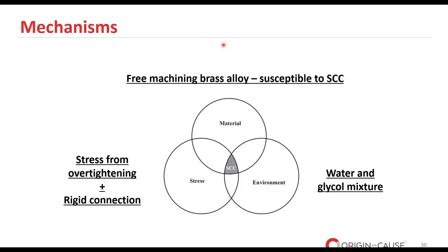So here's our SCC Venn diagram once more. On the one side, we have our brass alloy that's susceptible to stress corrosion cracking. The component's persistent exposure to the water and glycol mixture introduces another layer of concern. And also the combination of over-tightening induced stress and the rigid connection fostered some stress accumulation here. So we have our three requirements for stress corrosion cracking: stress, a susceptible material, and the environment, and these all collaborate to increase the risk of stress corrosion cracking in this context.